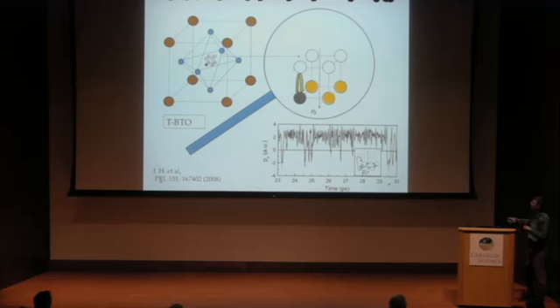But from time to time, the polarization is oscillating up and down. But sometimes it goes to the other minimum, which is no longer occupied. So on average, the other 4 sites are also a little bit occupied. So this is what we can see in simulations.